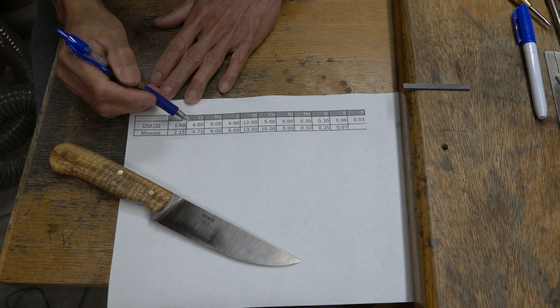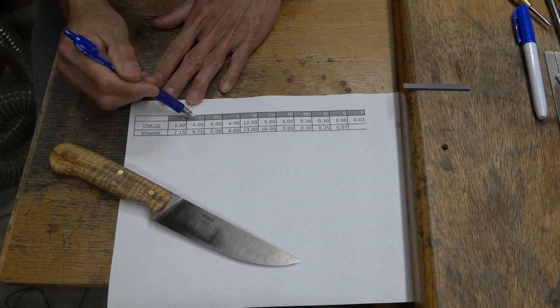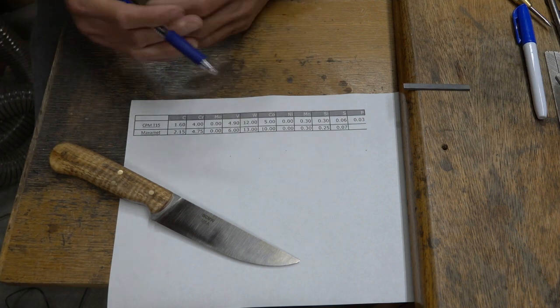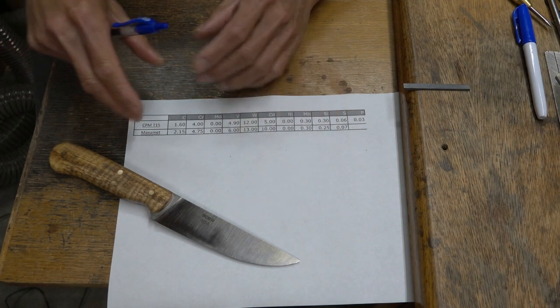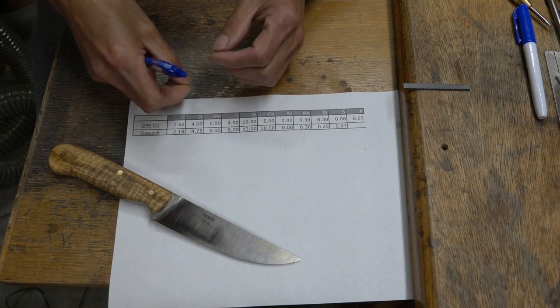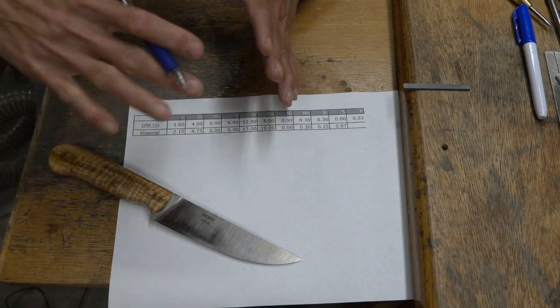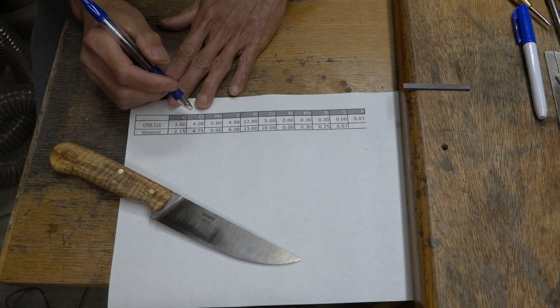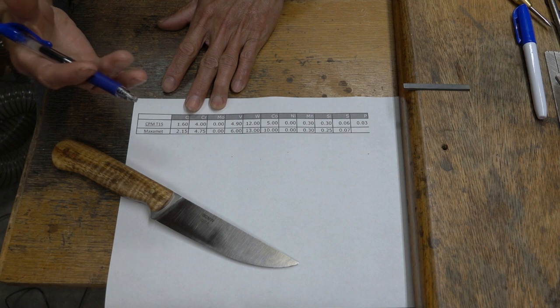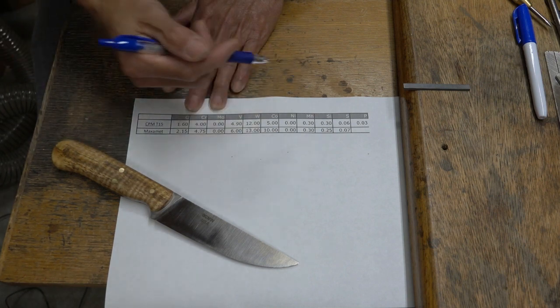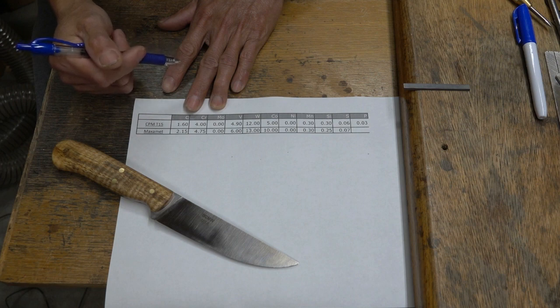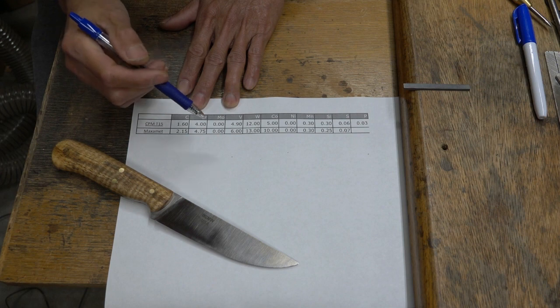So anyway, chromium. Most of the time when we talk about chromium, we're thinking of corrosion resistance. You create pretty much free chrome in the matrix, distributed around the matrix. And when you get oxygen, it creates more oxide with chromium to create a layer, a passivation, to protect. In other words, they already have that layer. It's no longer porous, so oxygen can't go deeper to interact with iron and carbon, but mainly iron.